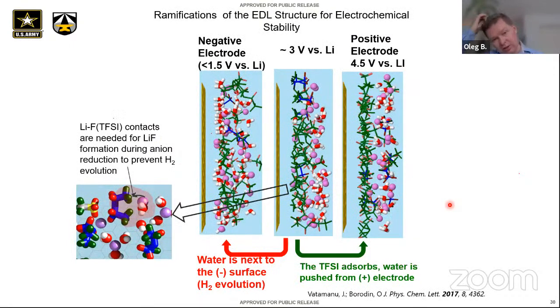Now, I want to summarize this picture of how the double layer is influencing at pretty high potential, so not very negatively polarized. There is an excess of anions, which is beneficial for preferential decomposition. What is pushed out, especially at the cathode, indicates that there could be an additional mechanism for stabilization of oxidative stability of water-in-salt electrolytes.